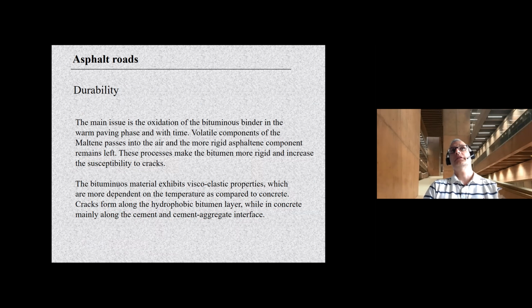If we have a look at the durability issue of asphalts, we can see that the main issue is actually the oxidation of the bituminous binder in the warm paving phase or during the time. And sometimes the volatile component of the organic binder, actually the maltenes, passes into the air, they evaporate, and the more rigid asphaltenes remain as a component left. And this process actually makes the bitumen with time more rigid, and with time then increases the susceptibility to cracks.